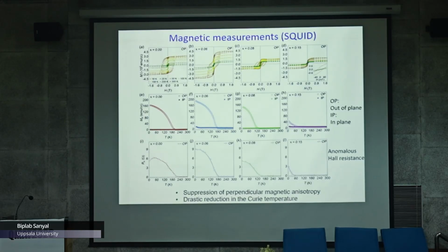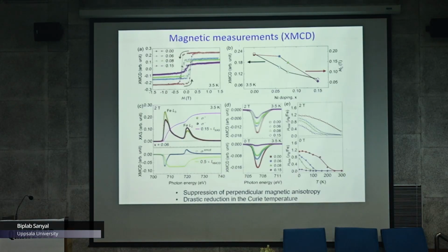One is that the perpendicular magnetic anisotropy is suppressed, and also they have seen a decrease in the Curie temperature. So this is also verified with XMCD measurements, and you see, I don't have time to go into it, but with the XMCD signal as a function of the concentration of nickel, you see that the signal changes, and also the magnetic moment changes with temperature. So basically, by these two methods, they have come to this conclusion.